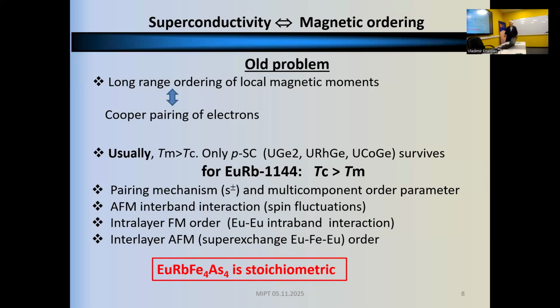interesting. So usually superconductivity develops at temperatures much lower than the magnetic ordering temperature, the Néel temperature. But in this material, it happens in just the opposite way. The superconductivity starts first, and then upon cooling, magnetic ordering sets in. The pairing, as in all other iron-based pnictides, the pairing mechanism is believed, and probably this is the case, to be due to spin fluctuations, and this is a multi-component order parameter.